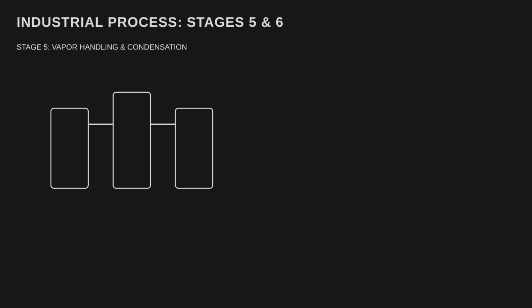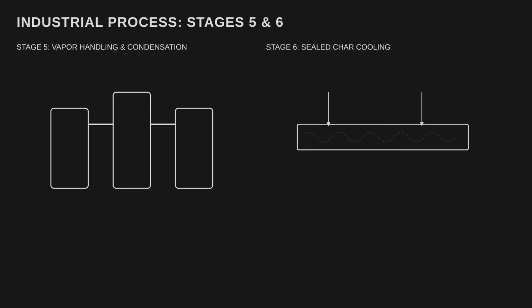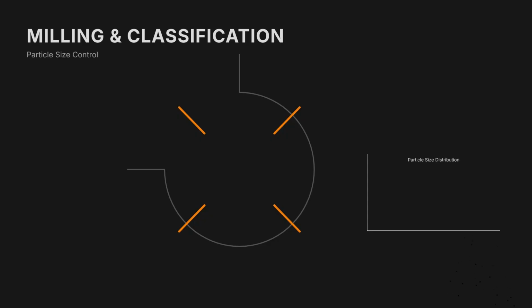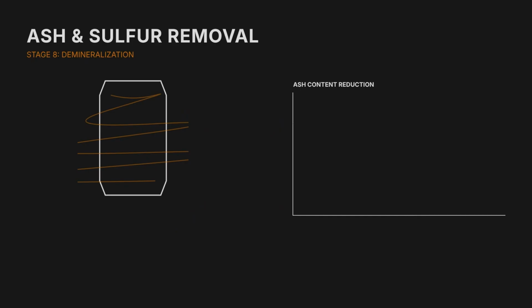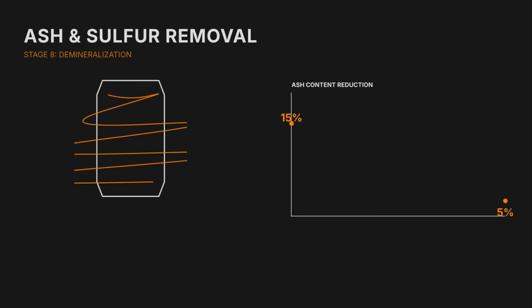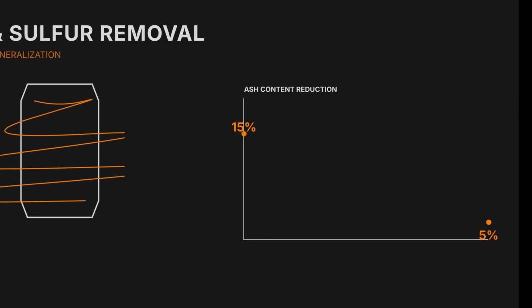In Stage 6, the solid char is cooled in a sealed inert atmosphere. If the hot char contacts air, it can oxidise or ignite, making this a critical safety stage. Stage 7 is grinding. Raw char particles are large and irregular. Milling reduces size and breaks agglomerates. A modern plant targets a specific particle size distribution to ensure good dispersion in rubber and plastics. Stage 8 is demineralization, one of the most important steps. Chemical treatment, like acid washing, is used to remove mineral ash and sulfur. This transforms low-value char into a serious industrial raw material.